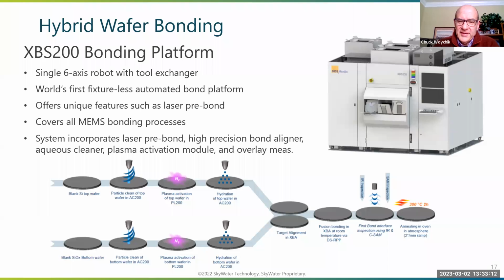And then after that, they're subsequently annealed to get the proper oxide bond, and then the extrusion of the copper into the surfaces. So this just clearly shows the stages of the XBS200 tool, but again, this is being currently practiced at SkyWater in our Florida facility, and we have shown success when we can do it with a silicon-silicon 200 millimeter platform for hybrid bonding and for oxide bonding.